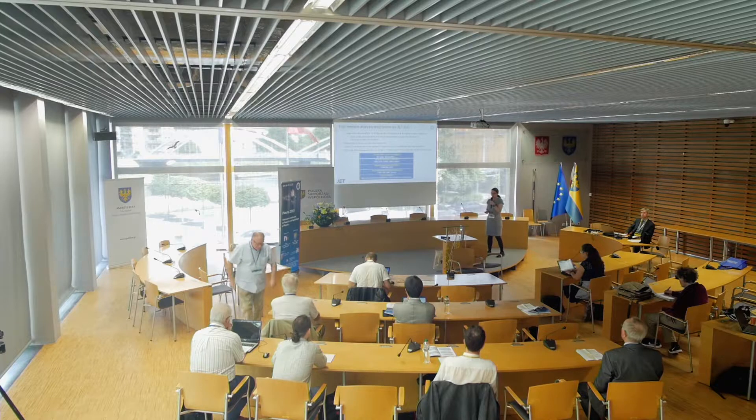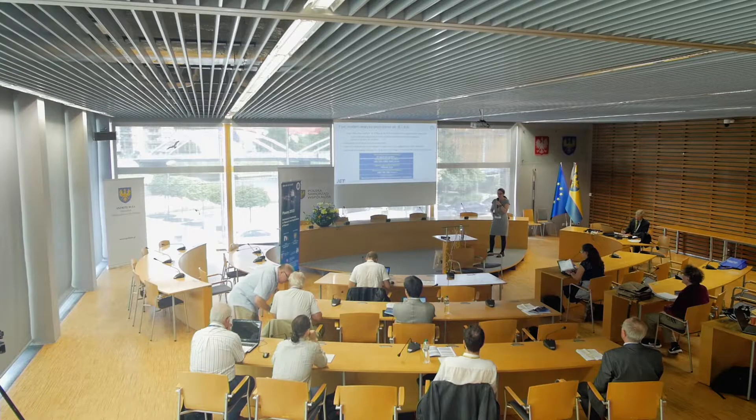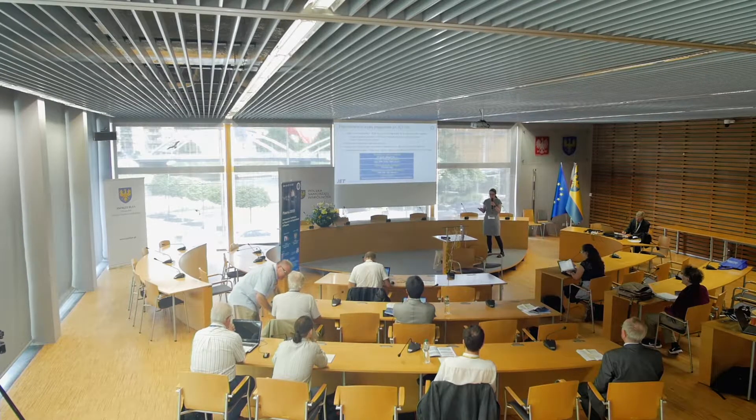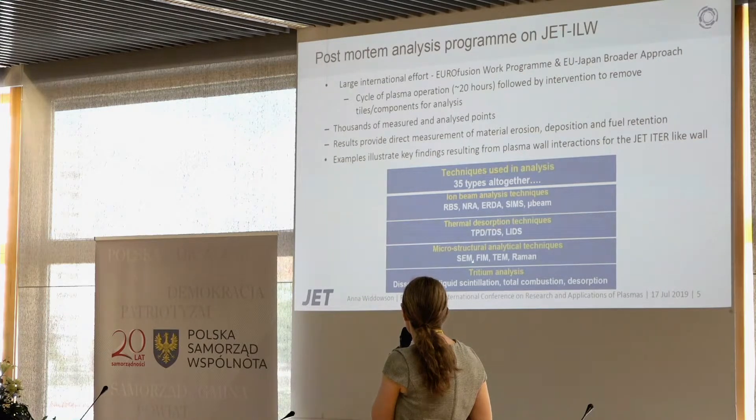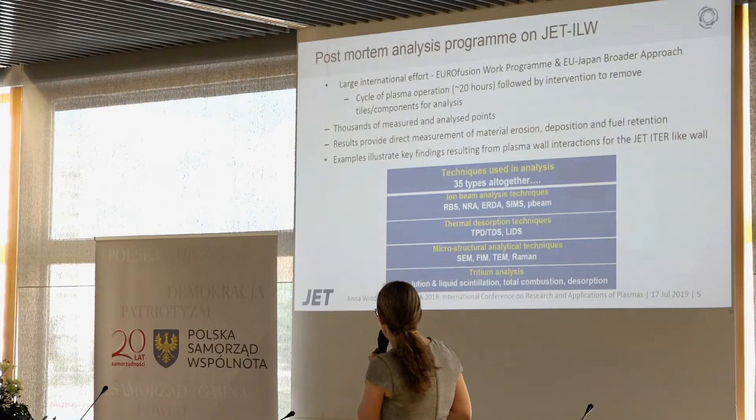The analysis of these tiles is a large international effort with samples distributed all over Europe, and we also have an EU-Japan broader approach collaboration. We have thousands of measured and analysed data points providing direct analysis of how materials are eroded, deposited, and the fuel retention. Techniques include ion beam analysis — backscattering, nuclear reaction, elastic recoil, SIMS, microbeam — plus desorption techniques such as temperature desorption and laser-induced spectroscopy, electron microscopy, Raman, and tritium analysis tools.